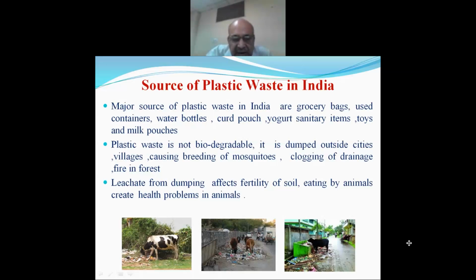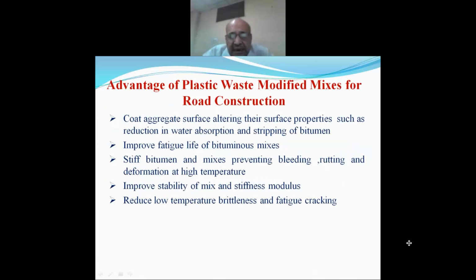If we consider the plastic waste, the optimum dose is 6 to 8% by weight of bitumen. At the same time, if we consider crumb rubber from tires, the optimum dose is 8 to about 10%. Therefore, roads are a better candidate for use of this non-biodegradable waste, particularly in our country.